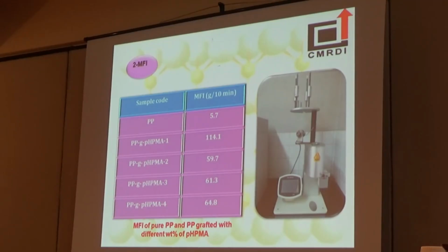If the material has a high melt flow index value, this means that it will have a low viscosity and vice versa. By measuring the melt flow index for all the prepared samples and for pure polypropylene, we have seen that the value of melt flow index increases greatly by grafting of polypropylene with 1% of p-hydroxy-N-phenyl maleimide monomer.